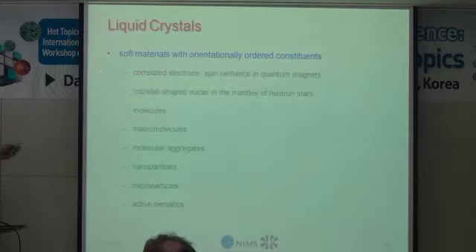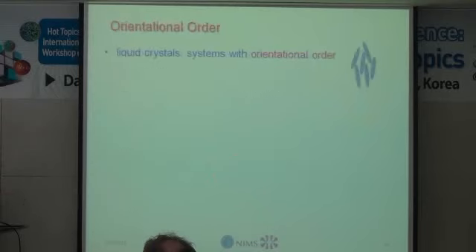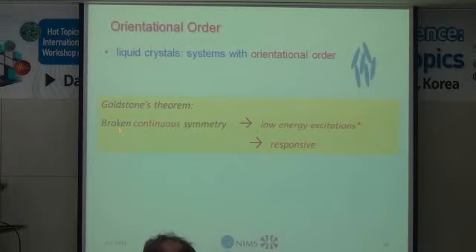So there's an enormous range of length scales and range of materials, all of which show liquid crystallinity, and this is all associated with orientational order. Now, orientational order has one key consequence. So there's this well-known Goldstone's theorem that says that broken continuous symmetry must give rise to low-energy excitations, and therefore these materials are exceptionally responsive.